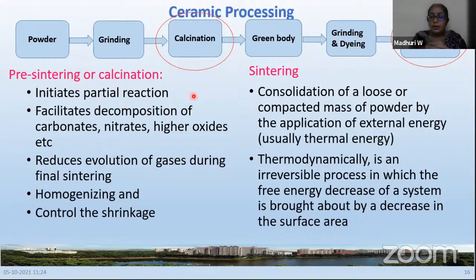Why? Because these are powders, there is no other chemical reagent you are putting in so as to initiate any reaction between them. Because I still don't want my final product as zinc oxide and ferric oxide, but I want it as zinc ferrite. When I want it as zinc ferrite, I need to initiate a reaction between zinc oxide and ferric oxide. So you need to see to catalyzing the reaction. Here the best way is heating it to a certain extent. Fine. So that actually facilitates initiating the partial reaction.